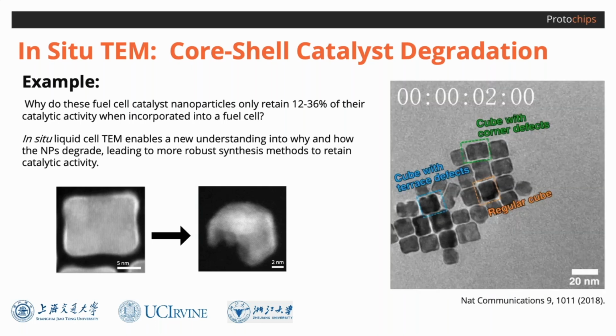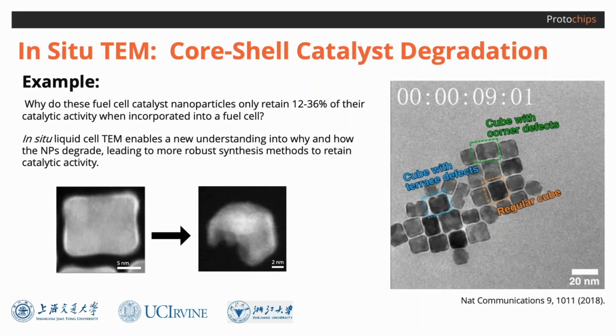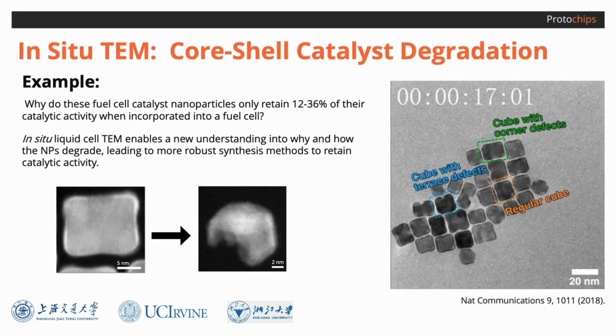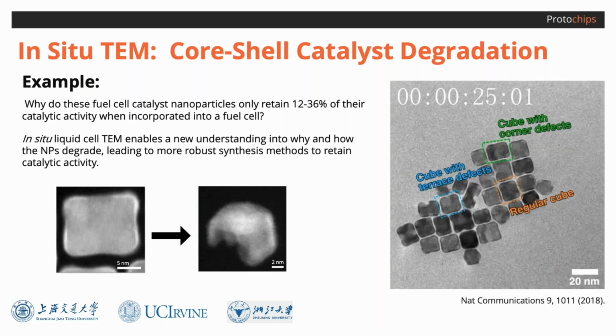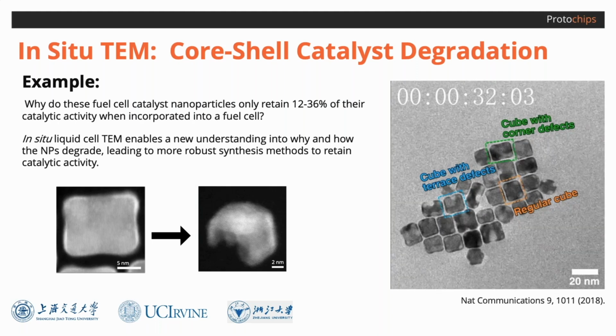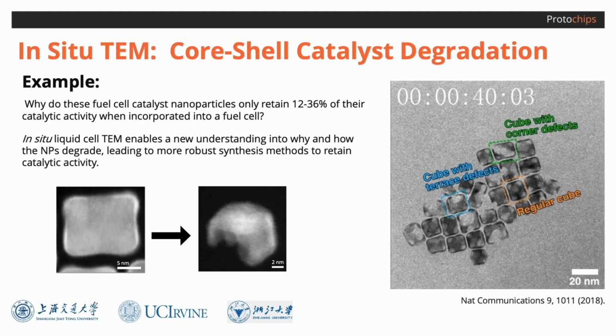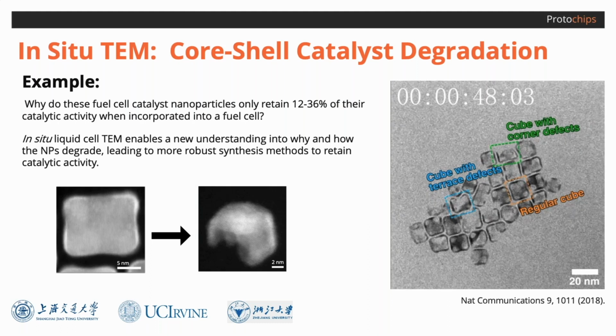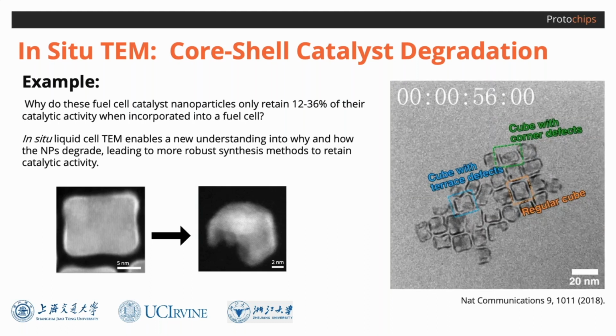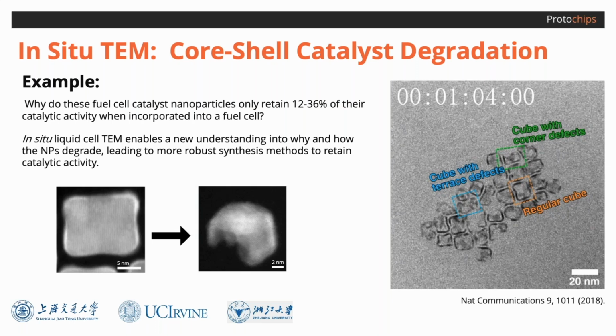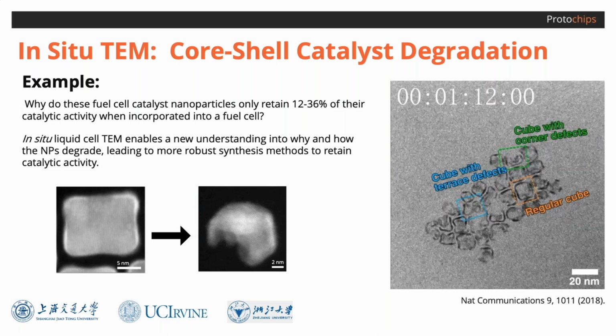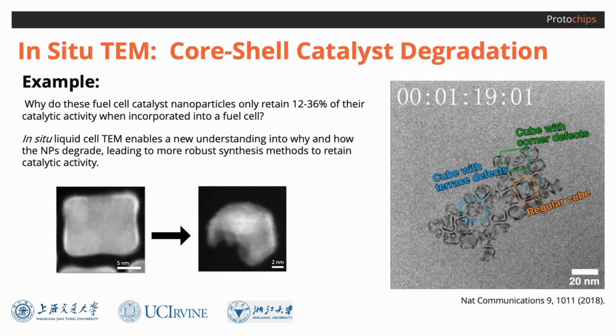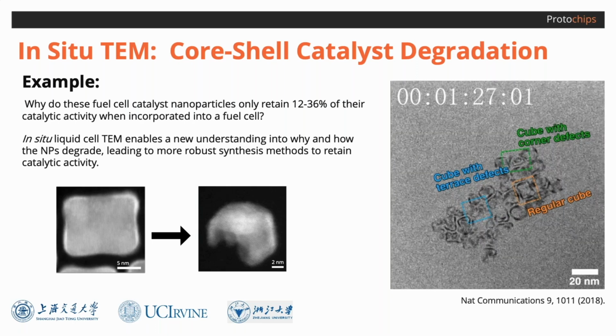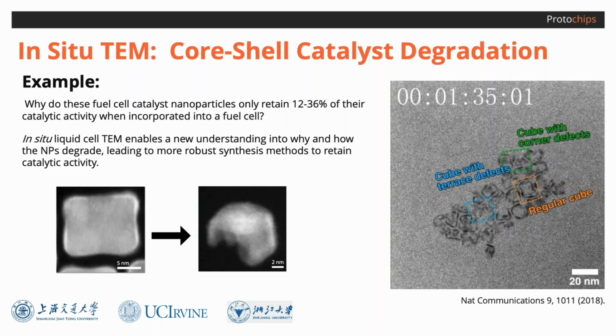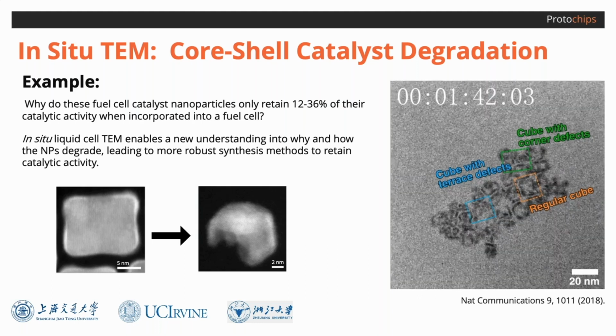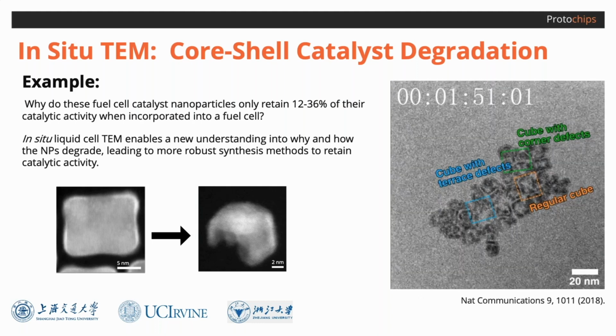Using in situ liquid cell TEM, researchers were able to observe and follow the degradation of individual catalyst particles in real time. This allowed researchers to pinpoint how different types of defects in the particle's platinum shell made them susceptible to different corrosion mechanisms. They identified 3 categories, color-coded in this movie: regular cubes with no defects, circled in orange, cubes with defects along the terrace, circled in blue, and cubes with defects at the corners, highlighted in green.